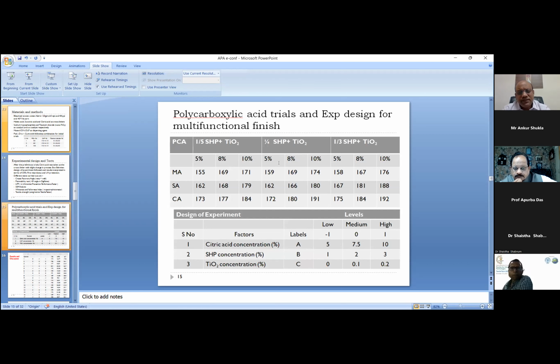So this is the initial trial which was taken. Here you find that the crease recovery angle is not very high. Finally, among these, the citric acid gave relatively better results. And obviously, because of more carboxylic acid groups, as I just told you, there is a possibility of higher cross-linking with the cellulose hydroxyl group.